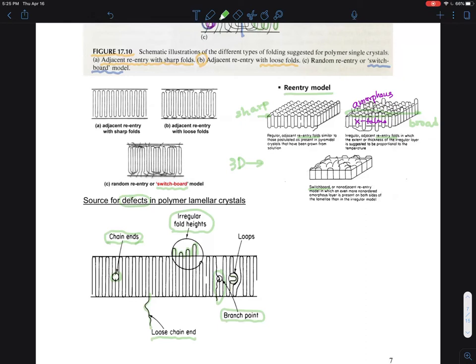Sometimes they make little hiccups, right? Little bubbles, little loops in the chain packing. So that causes some defects. The more defects that you can have, something looks like that. And it will reduce the melting temperature of the polymers and also affects the thickness of the lamellar crystal.